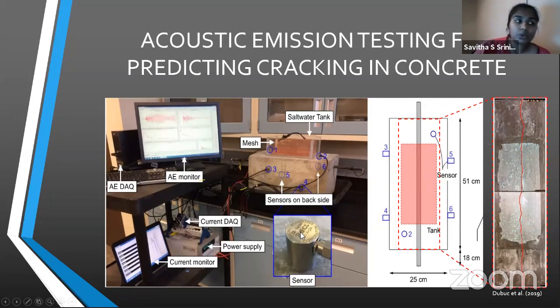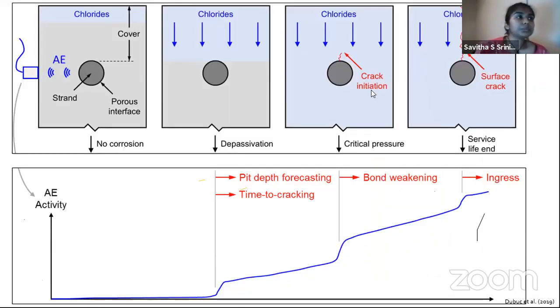we attached acoustic sensors to the end of each of these samples and just let it run. So when the concrete does crack, it'll release an acoustic pulse, which is picked up by the sensor and stored in the data acquisition system. So what we have here is how cracking progresses in a concrete specimen.